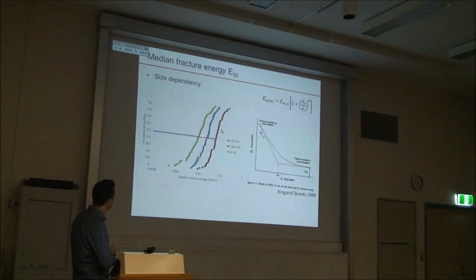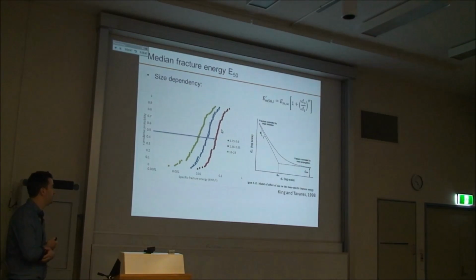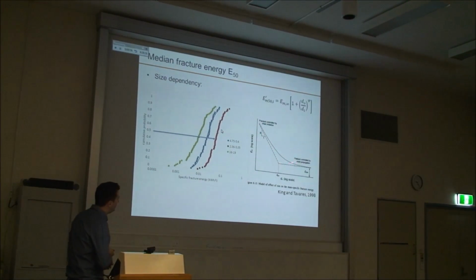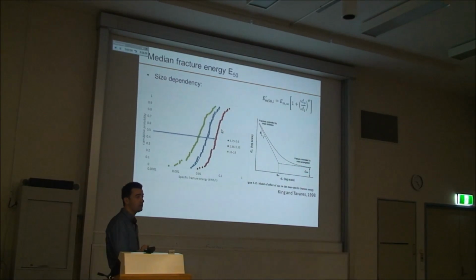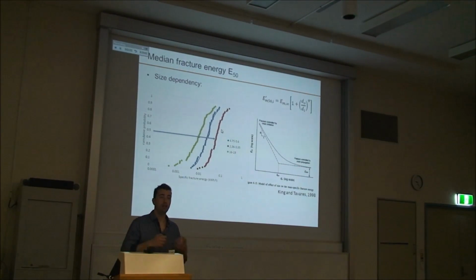So when you take this energy value and the size, you plot it on a log-log scale, and what you observe is this. So this is a quite important relationship. And there is a model that follows this trend. What Marcelo observed is that when the particles are large, the fracture is controlled by crack propagation. When the particles are large, and it could be a pebble of 50 millimeters, there are a lot of cracks, a lot of damage, faults in the particle. And the fracture is controlled by the length between those cracks, the distribution of those cracks in the particles.